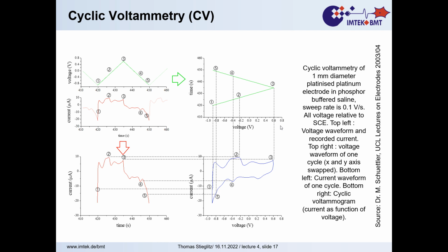We have the voltage course, which is triangular, upper left-hand side, and we measure the current. If we then plot the current over the voltage, here for one complete cycle, this is a real curve with 100 millivolts per second slew rate on a platinized platinum electrode. That means we have put rough platinum on the surface to see even more reactions on a given geometrical area. We see those oxidation and reduction peaks here, these bumps.